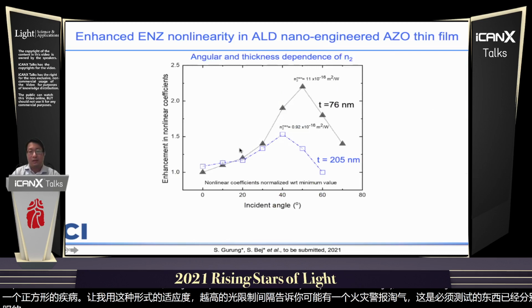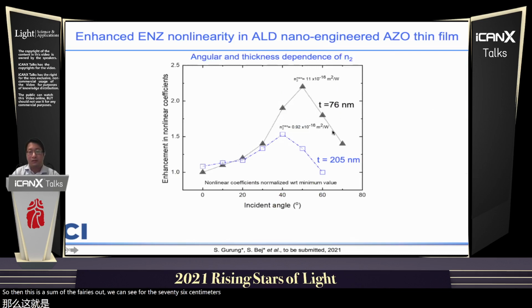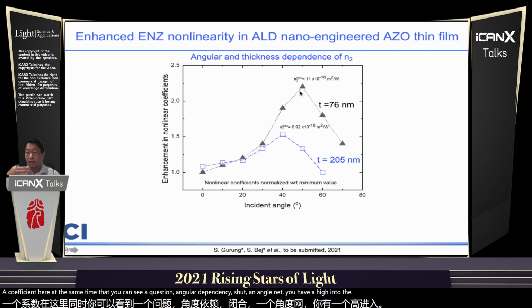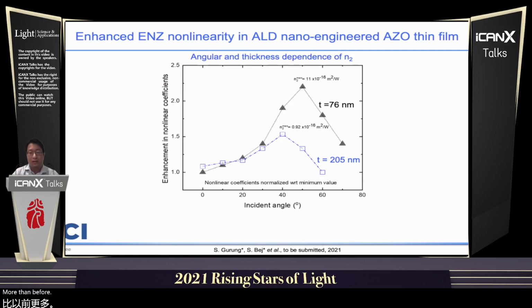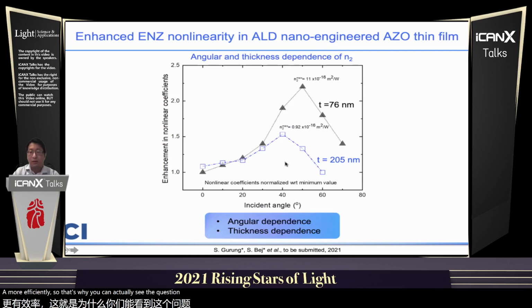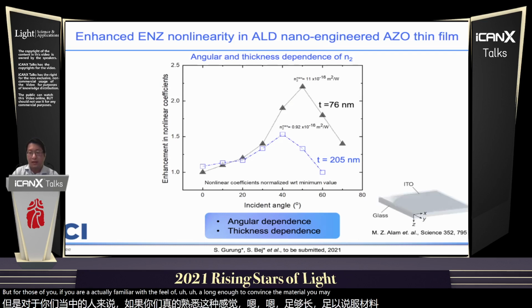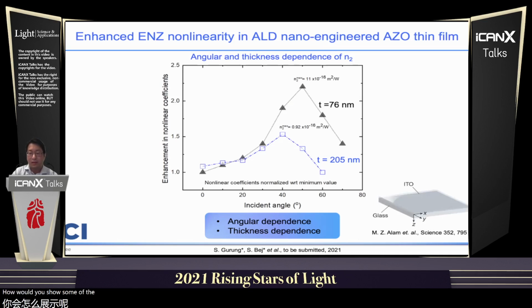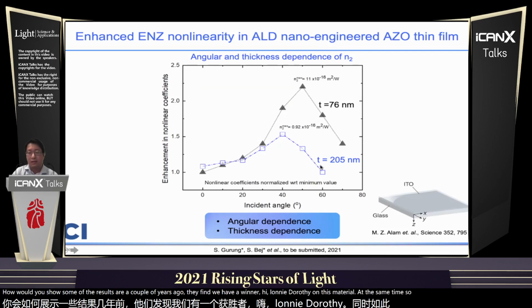So then this is some of the results we can see for the 76 nanometer thin film. A thinner film actually has a higher n2 nonlinear coefficient here. At the same time, you can see a quite strong angular dependency. At certain angles, you actually have a high n2 because you excite the ENZ mode more efficiently. So that's why you can see quite strong angular and thickness dependency here. But for those of you who are familiar with the field of nonlinear optics in ENZ material, you may find that Robert Boyd's group already showed some of the results a couple of years ago. They found a really high nonlinearity in this material, and also this kind of angular dependency, maybe not the thickness dependency, but they showed quite strong angular dependency here.